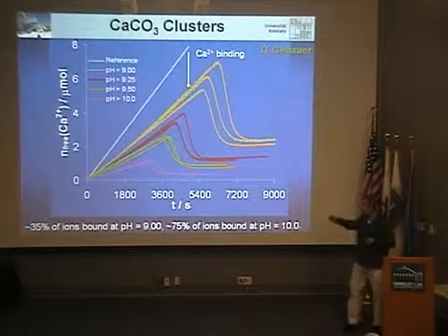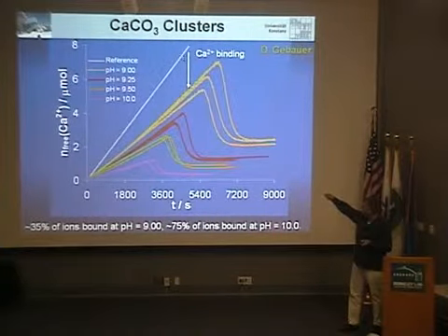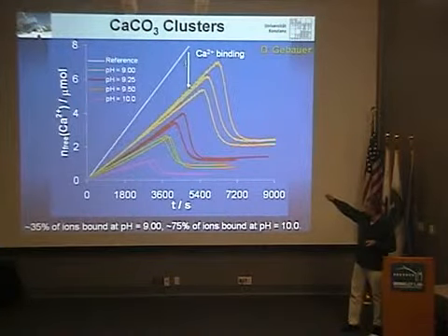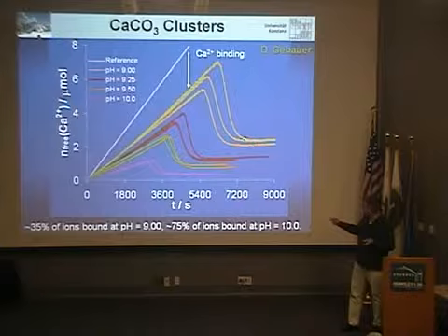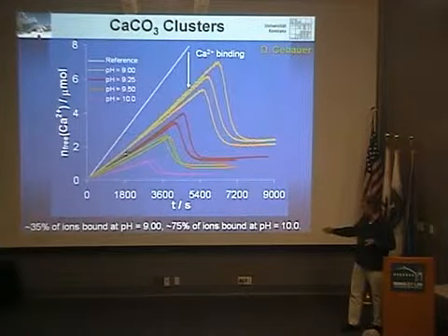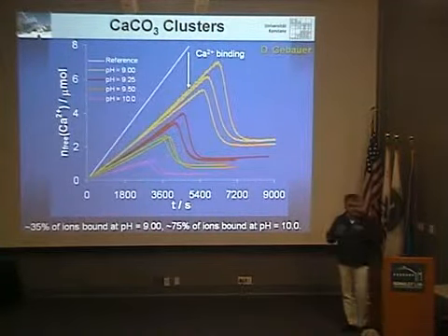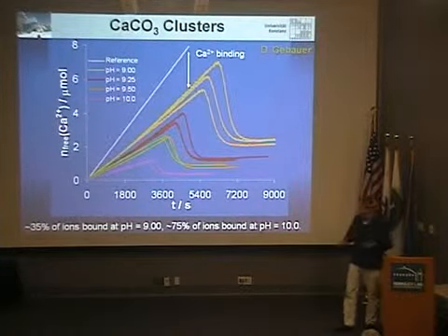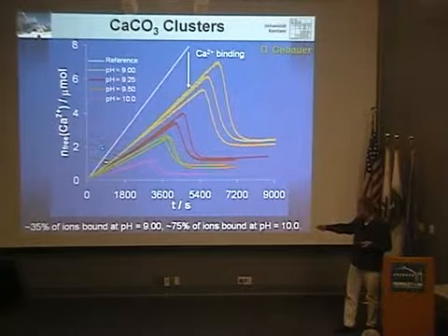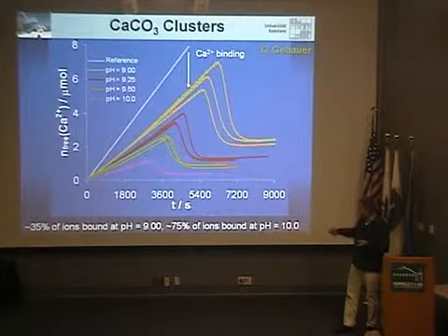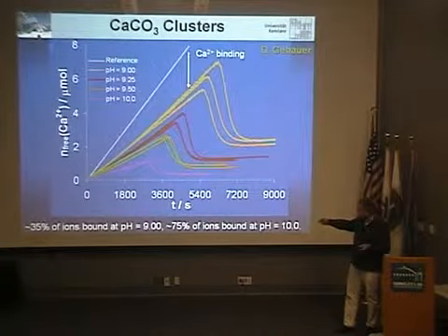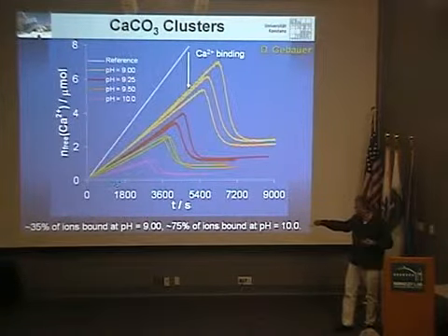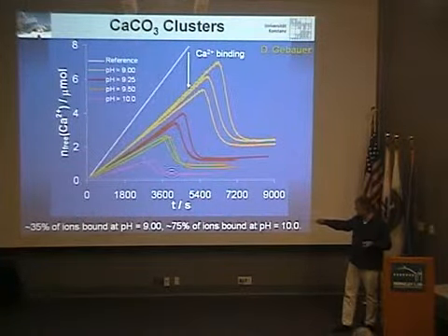And the important point now is, if I compare the calcium which I added, and that's the white curve here, to the calcium which I detect in solution, I always detect the difference. And more importantly, if you define the solubility product here, you see that the difference is there straight from the beginning in the undersaturated solution. That means even when I don't have any driving force for crystallization or nucleation, I already have a difference between detected and added calcium. And that difference becomes even bigger the higher the pH. And it can be up to 75% at pH 10. That's the magenta curve here.